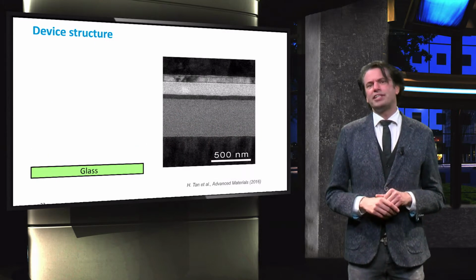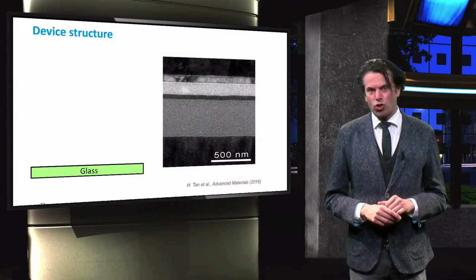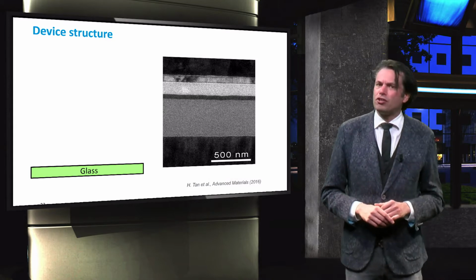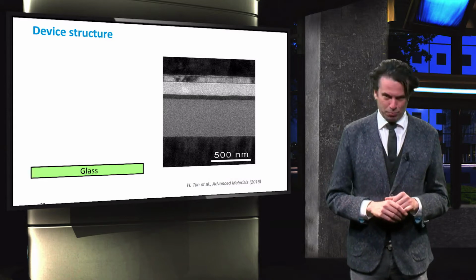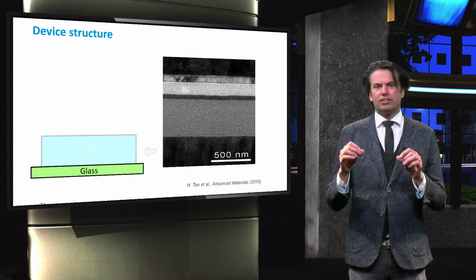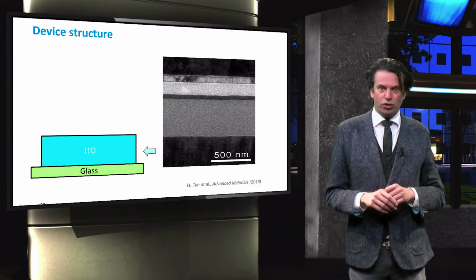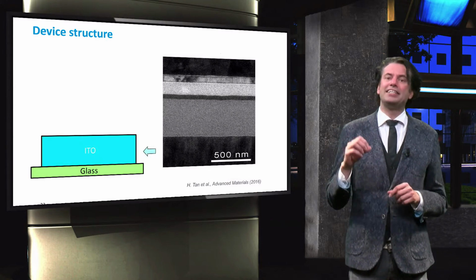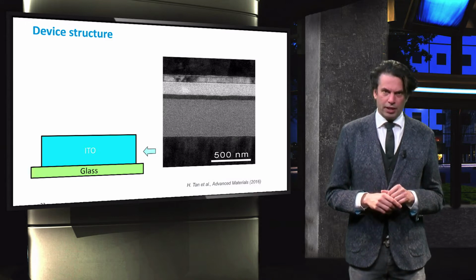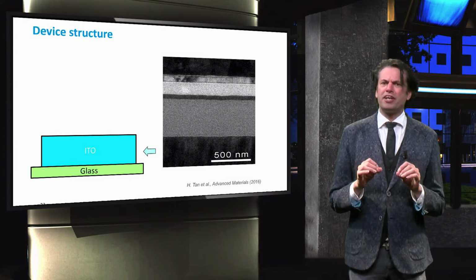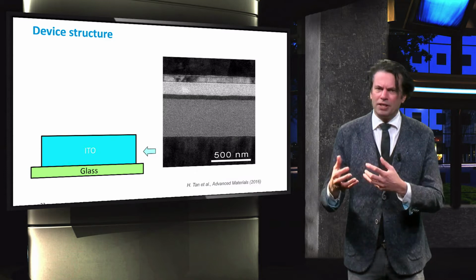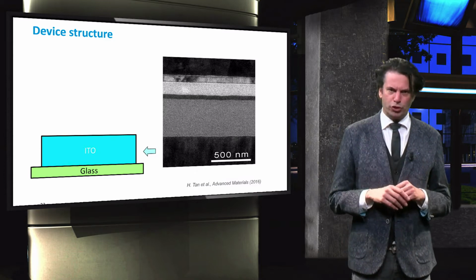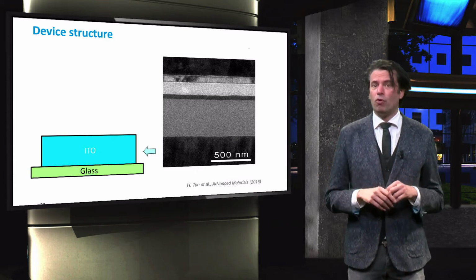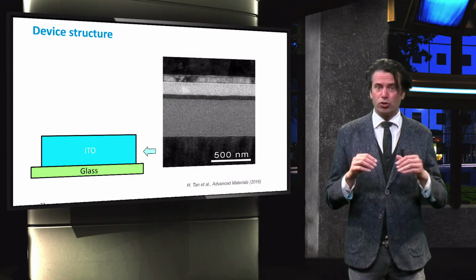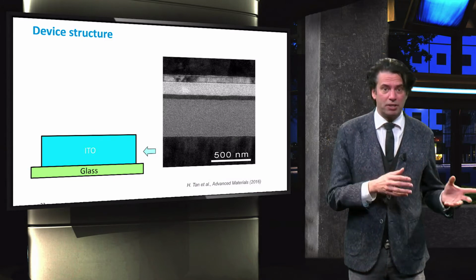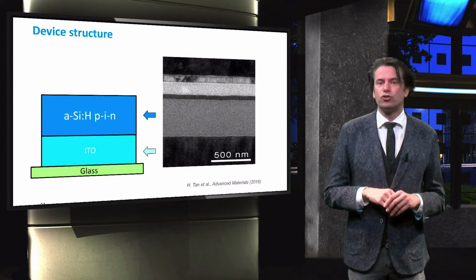Here you can see a scanning electron microscope picture of the cross-section of a hybrid multi-junction tandem solar cell. As a transparent contact layer on top of the glass substrate, ITO has been chosen. It is rather a challenge to integrate these different technologies in one monolithic integrated multi-junction device. As the amorphous silicon PIN junction is processed at higher temperatures than organic materials, the amorphous silicon top cell needs to be deposited first.